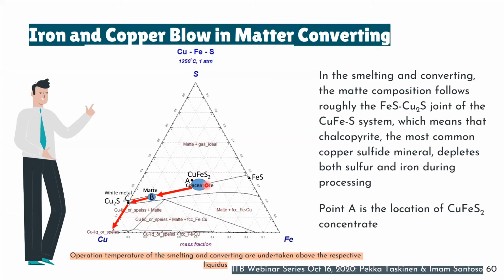So when it is melted in, like, a flash smelting process, the concentrate composition will move from point A to point B. We can see here during smelting from point A to point B, the copper concentration is increasing and the iron concentration is decreasing. So basically during matte smelting, we're removing iron and sulfur.